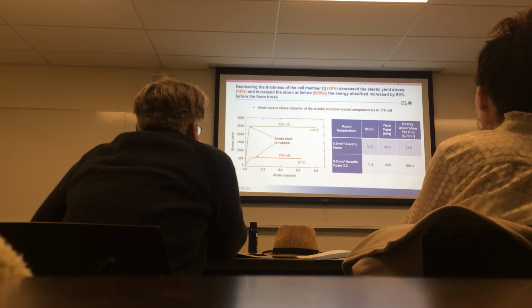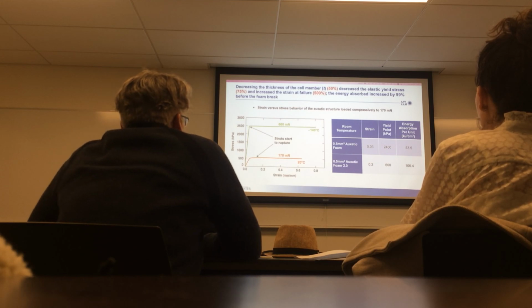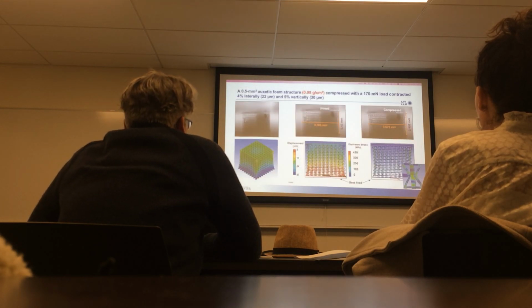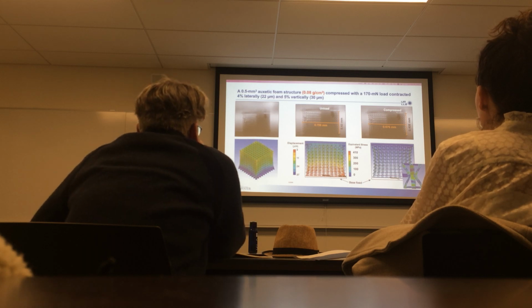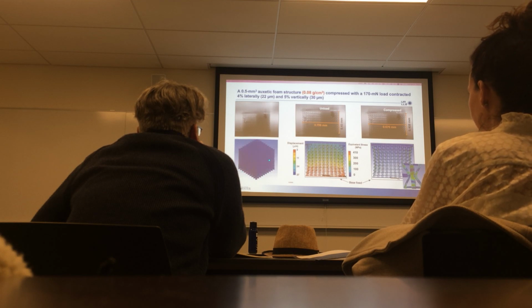And during the compression of the second generation foam structures, we observed shrinkage vertically, which means this foam structure has obvious negative Poisson's ratio behavior. When we apply the 170 milliNewton force on the top, there is a 4% strain in the lateral direction and 5% shrinkage in the vertical direction. And our simulation also proved this result.